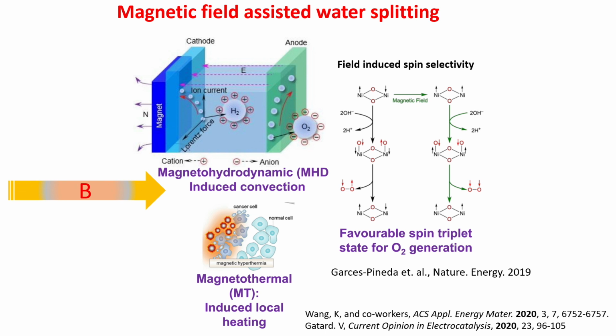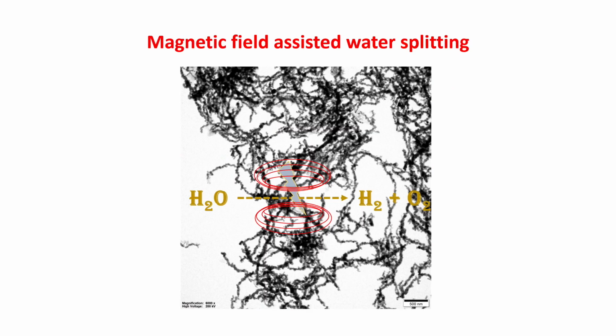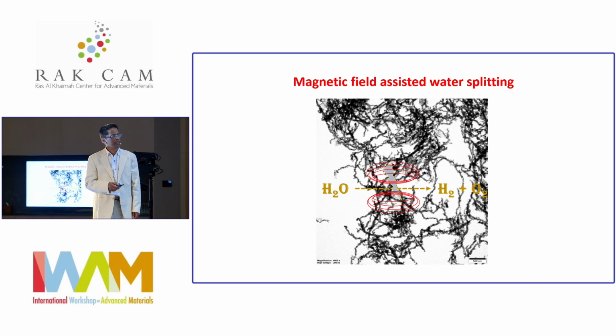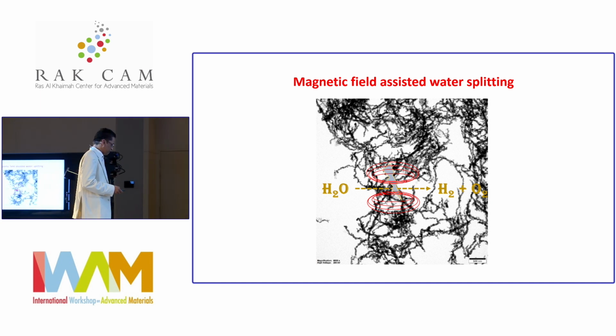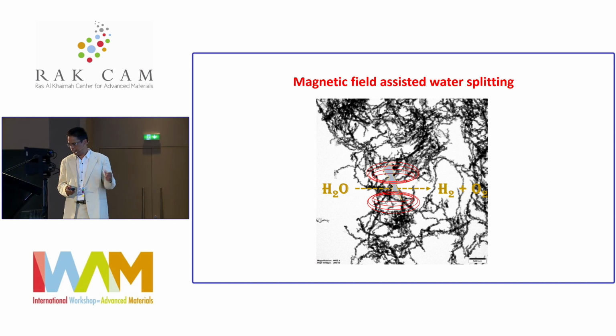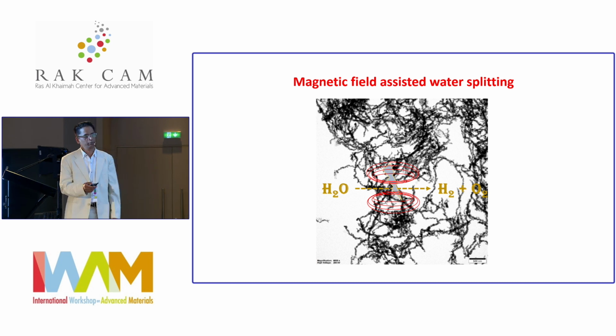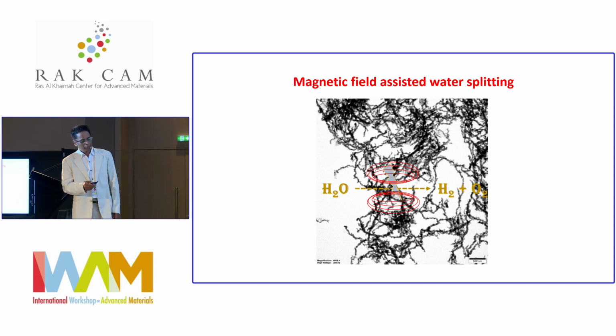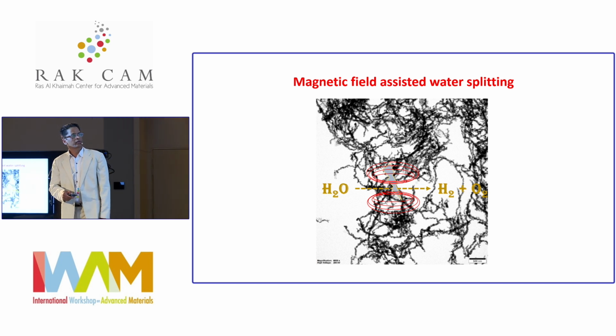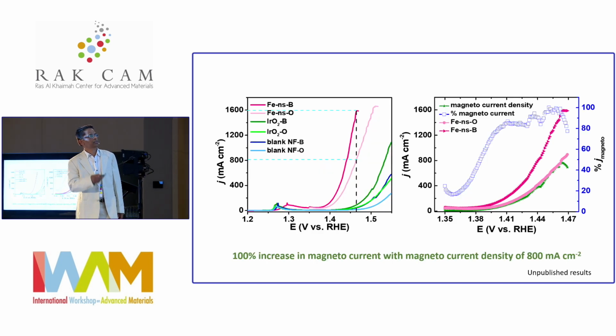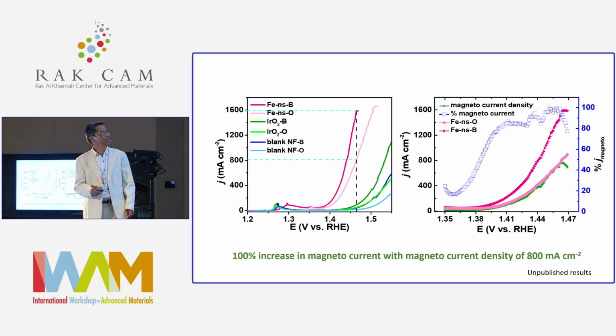So we looked at this kind of magnetic iron structure, a very nice nanostructure which we wanted to check for this type of magnetic field induced reaction, to see how it performs. We prepared it by a simple borohydride reduction of an iron precursor, and got beautiful nanostructures with filament-like structures due to the magnetic properties.